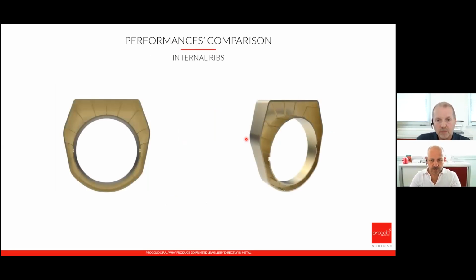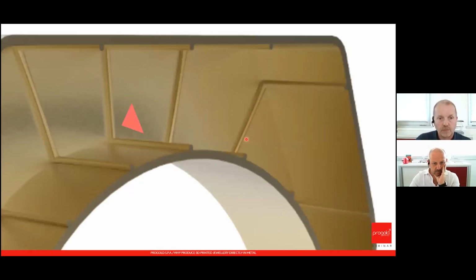I show you some internal ribs that you could provide, if you need to, to assure a structural reinforcement of your parts, particularly if you use a very thin wall thickness. It's not necessary if you use a standard thickness such as 0.35 millimeter. Probably you don't need these internal ribs, but it's possible to do it if you decide to select a very, very thin wall thickness, such as 0.2 millimeters, as we spoke before. And these are the ribs.